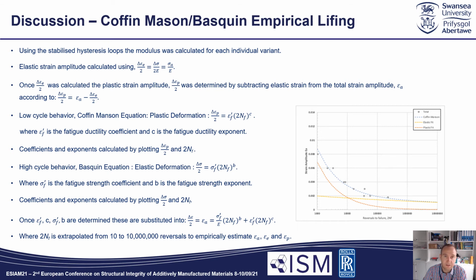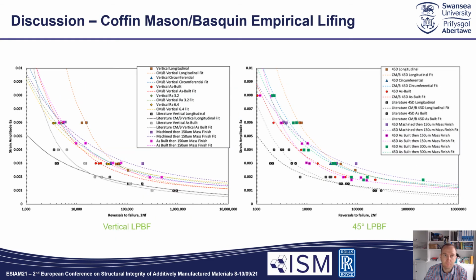For HCF conditions, so fatigue data beyond 100,000 fatigue cycles, where the material is predominantly deforming in an elastic manner, the Basquin approach can be used, which is calculated by the stress amplitude being equal to the fatigue strength coefficient multiplied by 2 times your fatigue life to the power of a fatigue strength exponent. Like for Coffin-Manson, these coefficients and exponents can be calculated by plotting the stress amplitude against your fatigue life values, multiplied by 2, and then using log-log axes. Once determined, these values can then be substituted into this long equation here in the last but one bullet point, to produce the data fits given in the two graphs here.